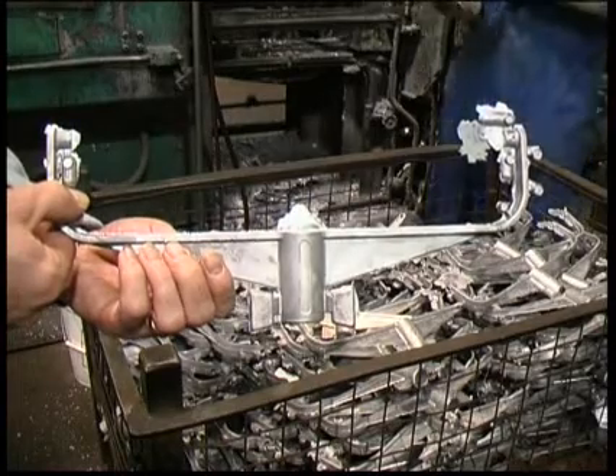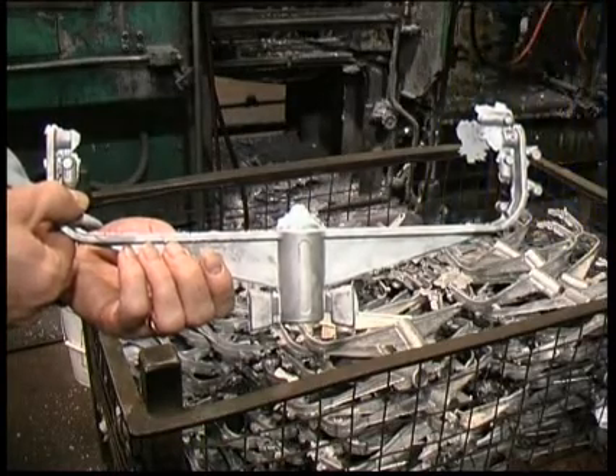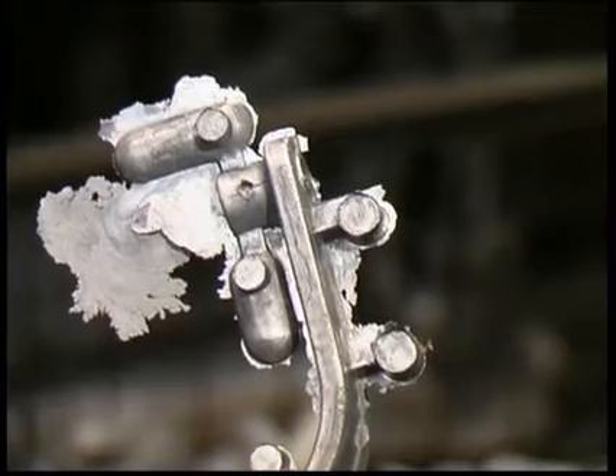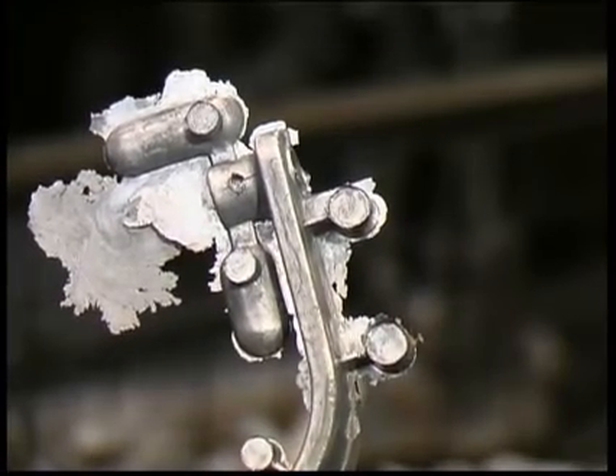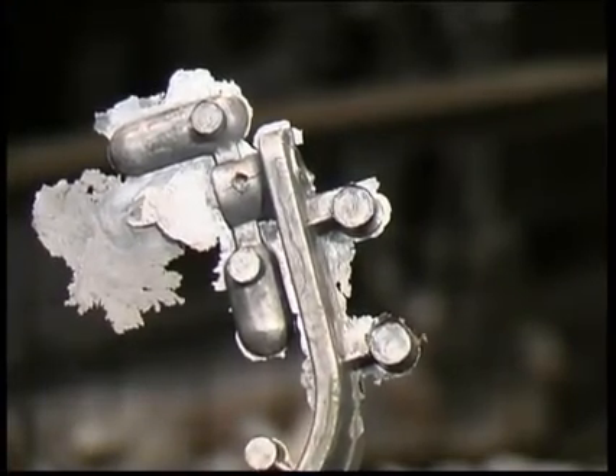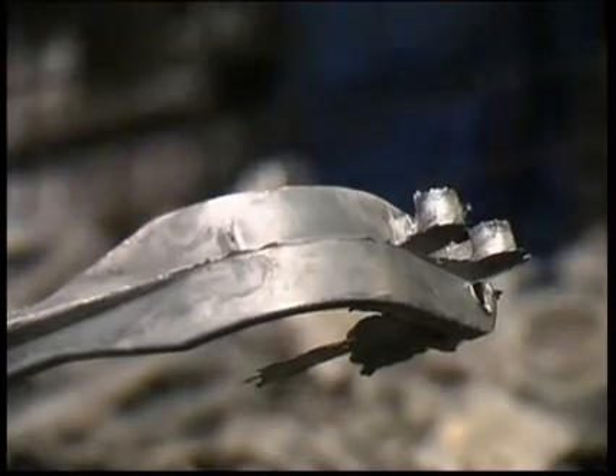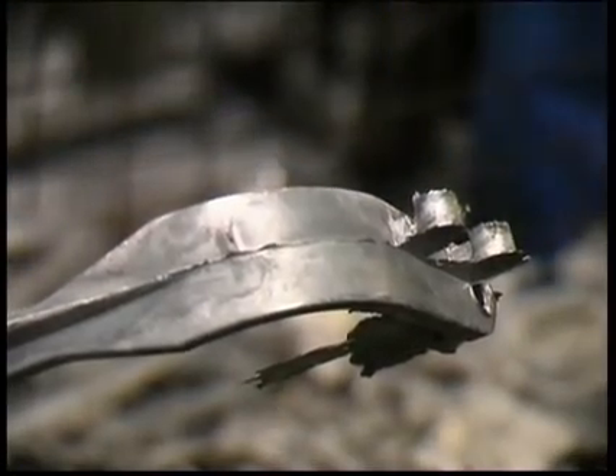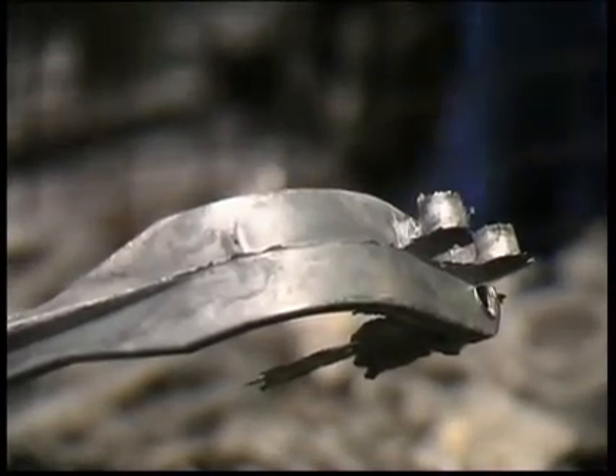Thin aluminium known as flash can be seen around the casting where the die has become worn and a good fit no longer exists. Here the split line can be seen indicating where the two halves of the die fit together.